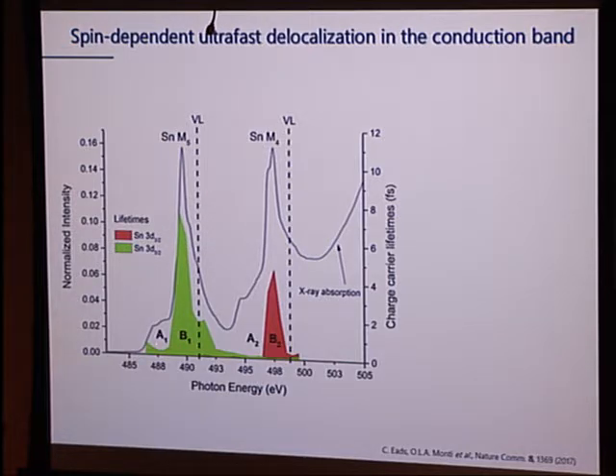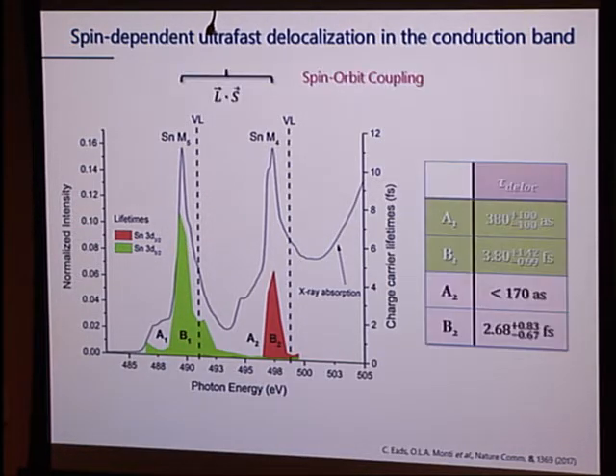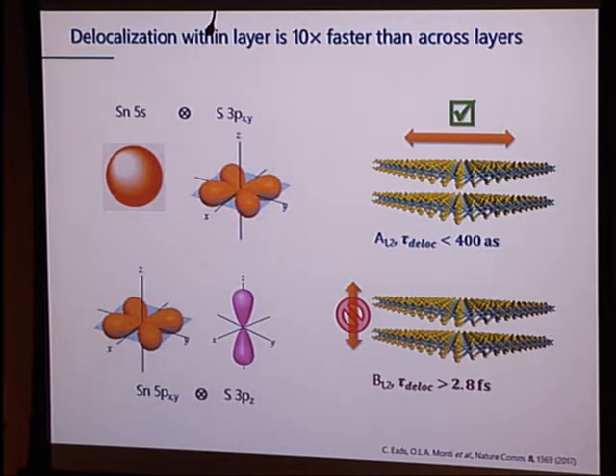If you look at the carrier lifetimes, you see there's a dramatic difference. In fact, quantitatively, our carrier lifetimes are about 400 attoseconds in the conduction band minimum region, but about a factor of 10 higher away from the conduction band minimum. I also want to highlight just how short these timescales are. Why is this? Near the conduction band minimum, that minimum is mostly made up of some Sn 5s and some Px,y orbitals that are in-plane orbitals, whilst away from it, we start to mix in Pz orbitals. So away from the conduction band minimum, we're probing processes that preferentially go out of plane, whilst near the conduction band minimum, we're probing processes that are in plane.